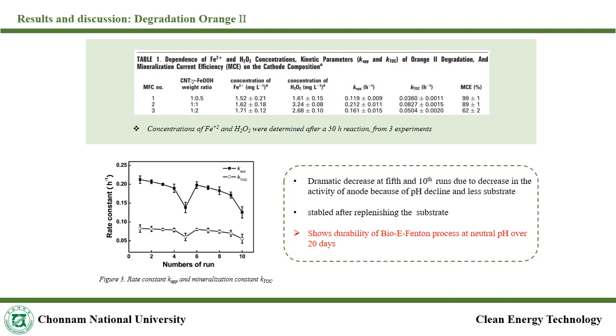Table 1 shows how the cathode composition affects hydrogen peroxide and ferrous ion composition, kinetic parameters of orange 2 dye, and mineralization current efficiency. Figure 3 shows that when the experiment was performed for 10 runs, there was a dramatic decrease in the constant values at the 5th and 10th runs due to the decline of pH and substrate. After replenishing the substrate, the values were stable.